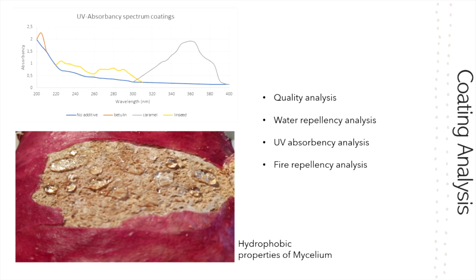The mycelium without coating already seemed not affected by water and fire. In addition, the quality of the coating was lowered by adding additives in such a way. The question should be asked if they should be cut from the coating completely. There was chosen to cut the additives that were expected to protect against outside effects.